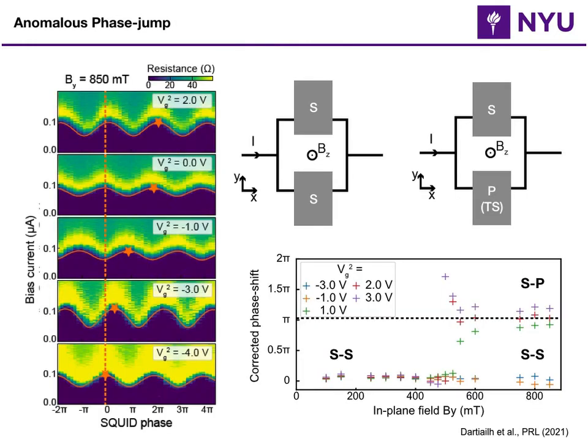By keeping both gate voltages at very low values, I will have an S junction and an S junction in a SQUID loop. So if I measure the relative phase between the two, it's going to be 0. That's what the measured phase shift has been showing. If you look at the graph at the bottom, when I have an S and S, independent of the magnetic field, you get almost a vanishing number.